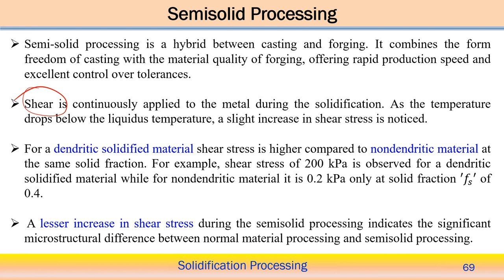Now if we compare dendritic and non-dendritic material, we can observe in which case the shear stress needed is more or less. For a dendritic solidified material, the shear stress is higher. So the shear stress required for dendritic solidified material is higher as compared to non-dendritic material, of course with the same solid fraction. With the same solid fraction, in the case of the dendritic structure, we need more shear as compared to the non-dendritic material. So that is the basic feature: depending on whether we control a dendritic or non-dendritic structure, the shear stress requirement differs much between these two kinds of structure.